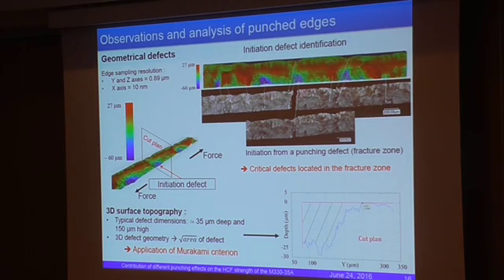So here is an example with the scan before fatigue testing, micrographs of the cracked specimen, and here is the defect on which the crack initiated. And of course, as I said, it's always in the fracture zone. So we get the 3D geometry of our defect with this resolution. First, we measure the square root of the area in order to assess the Murakami criterion. And well, I won't speak much about it because it didn't work. Mostly, we guess it's because we have very large gradients regarding hardening and residual stresses. So simply it's not suitable for this type of problem.